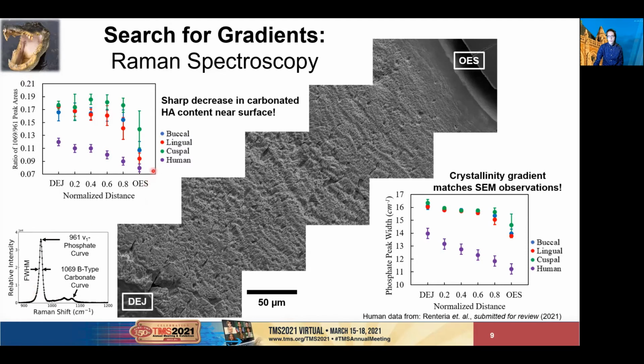Similar to humans, we see a gradient in alligators with the inner enamel being significantly more carbonated than the outer layer. And similar to the observations from our nanoindentation, the gradient is quite sudden. Compared to humans, alligator enamel has a significantly higher level of carbonated hydroxyapatite, though the difference is not quite so large in the outermost region. We also noticed that the measures of carbonate content were persistently higher for the cuspal surface, and we're still looking into that, since we didn't see any change in the nanoindentation.